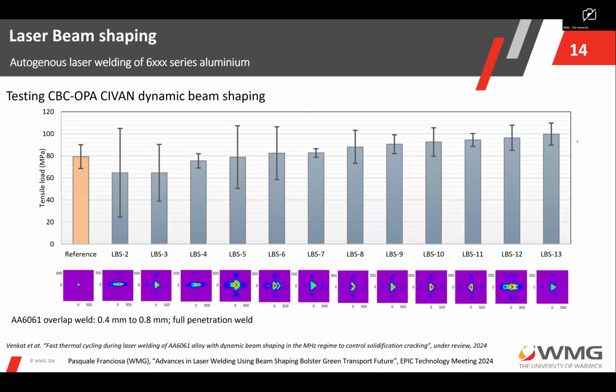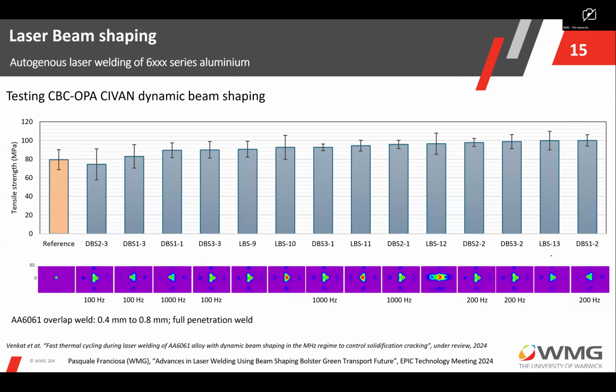It's almost 20% improvement only by changing the beam profile. And this is semi-static because it's only one shape. Then if you add the dynamic element, in this case we didn't go more than 1000 hertz, you can see again the trend. There is a margin for improvement.